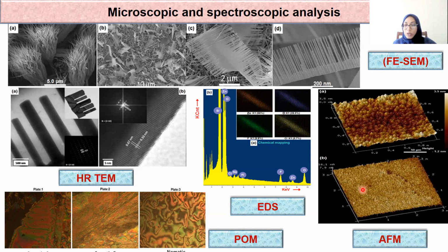Then conducting more atomic force microscopy helped to understand the surface current. And here the current measured was in the range of 7.9 nanoampere to 16.1 nanoampere. And this shows the polarization optical microscopy images. And here these are the images of various phases at different temperatures. And again here this is a clear indication that this is functioning as an electro-optic switch.